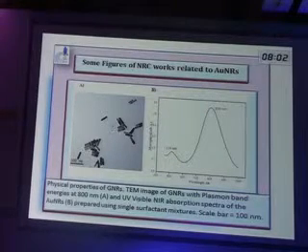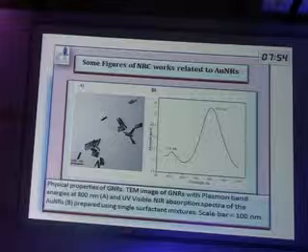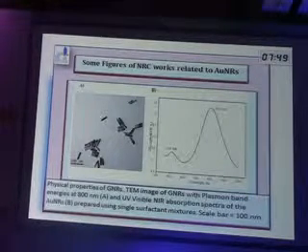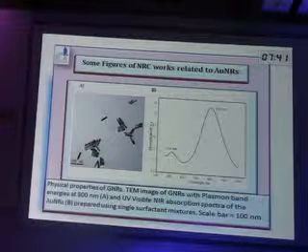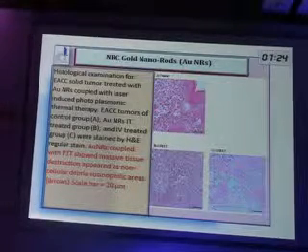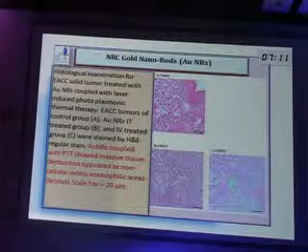This is the characterization of nanogold. It is carried out using transmission electron microscopy and UV visible spectrometry. Here we can see the absorption of the nanoparticles suitable to the biological window, and the nanoparticle size is small and homogeneous. Here we give the histology of the cells. Nanogold particles coupled with photothermal therapy showed massive tissue destruction, appearing as non-cellular debris. Here the scale is very small, 20 micrometers.